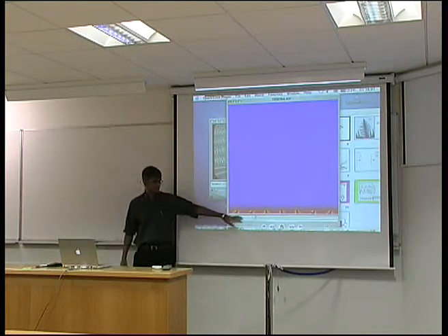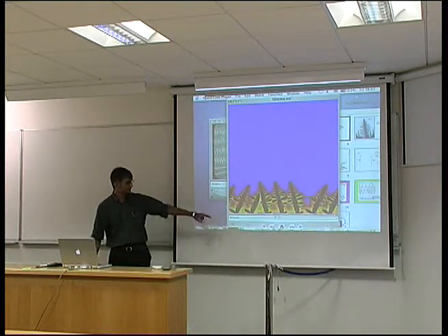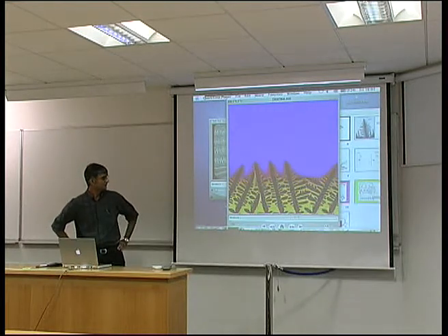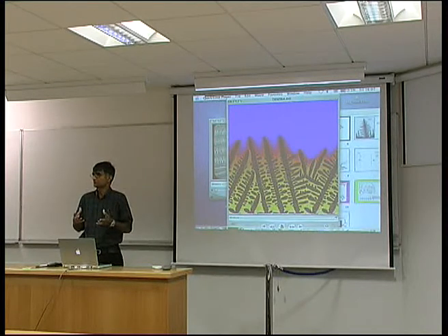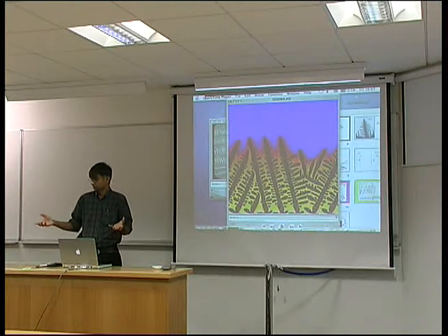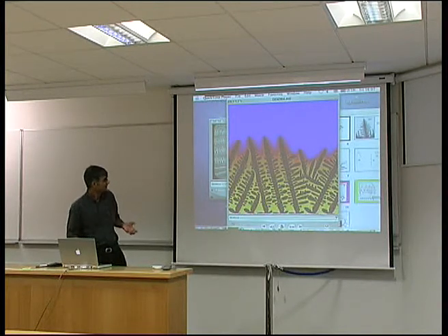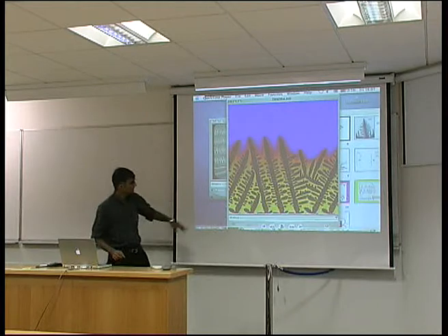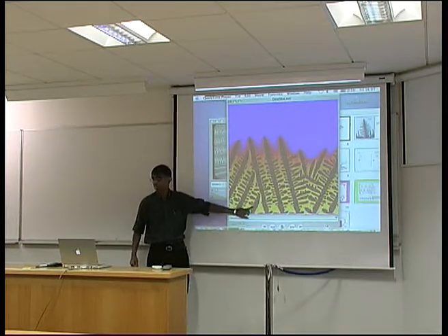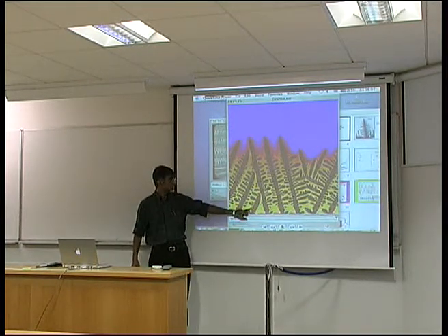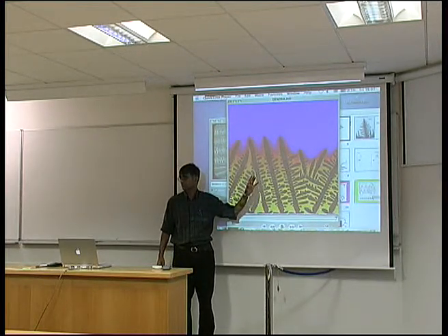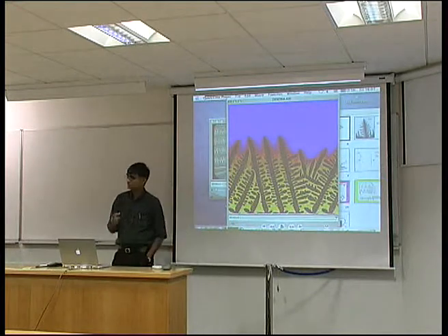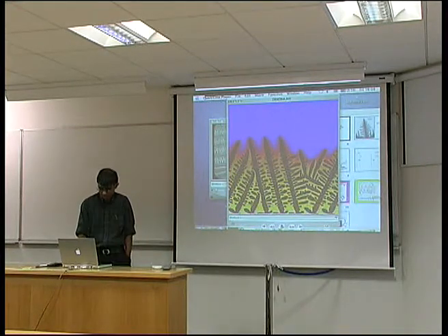So we're starting solidification from here, and we have a negative temperature gradient, and you can see a huge amount of branching of the crystal going on, because every time you have a perturbation, it tends to advance into supercooled liquid. Now, notice one other thing: we have crystals being stifled because they are not growing in the direction of maximum heat flow.